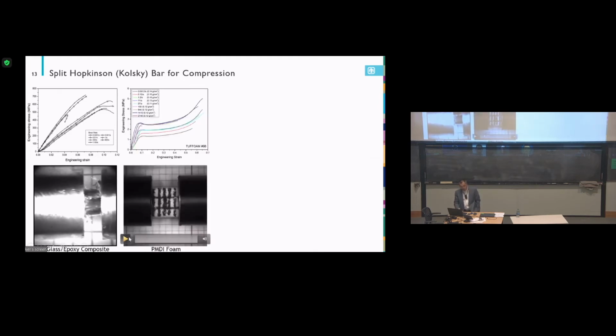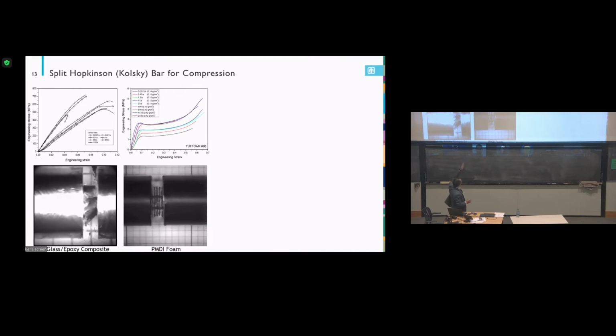And this is a foam material, so you can see how the foam just keeps compressing. You can see the linear elastic region, the yield, then the long plateau, which means all the cells collapse. Then until fully collapsed, they reach densification. So that's why the stress-strain curve goes up.